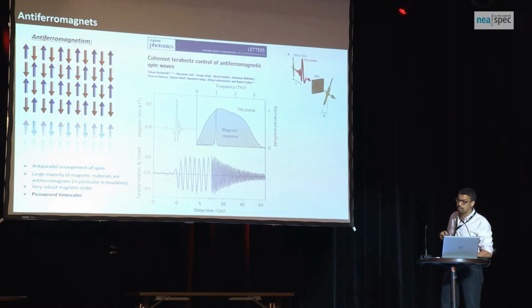Actually, the most interesting property for us lies in their dynamical properties, because their intrinsic resonance lies directly in the Terahertz range, as nicely illustrated by this work where they could measure the 1 Terahertz antiferromagnetic resonance in the prototypical nickel oxide crystals. In other words, these antiferromagnetic textures can typically be moved around on picosecond time scales. That is 3 orders of magnitude faster than their ferromagnetic counterparts, where all spins typically lie in the same direction.